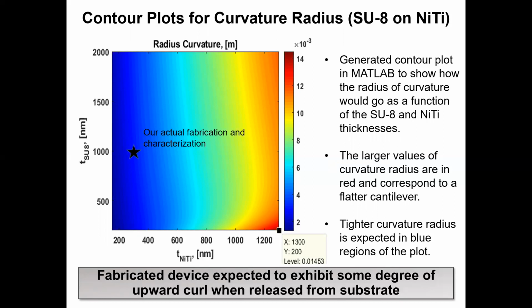I would say this result is somewhat intuitive because the thicker NiTi would be expected to be more rigid, and then the thinnest SU8 configuration would minimize the bending due to CTE mismatch, which for NiTi and SU8 is quite large at about 40 parts per million. Since the fabricated device was in the blue region, a large amount of curling would be expected upon release from the substrate. And this was later proved to be the case with real device fabrications and measurements.